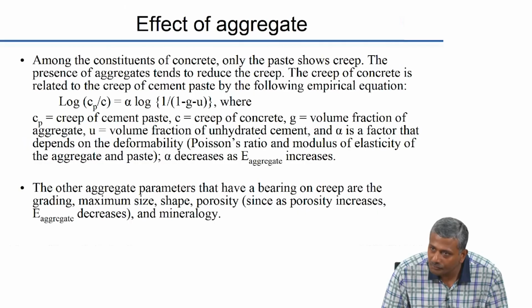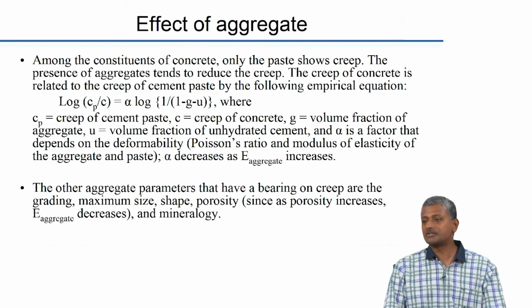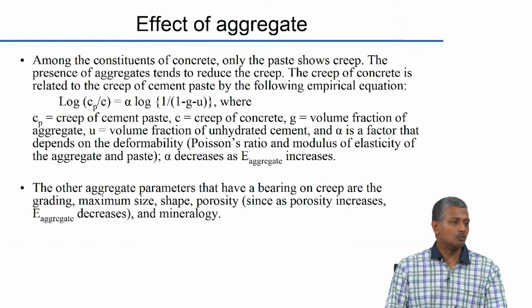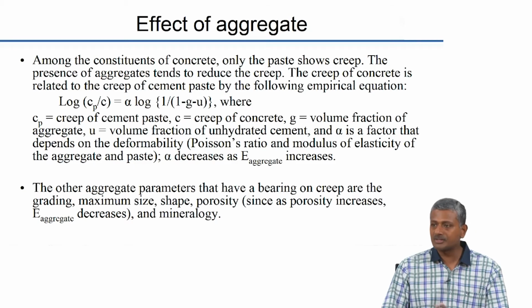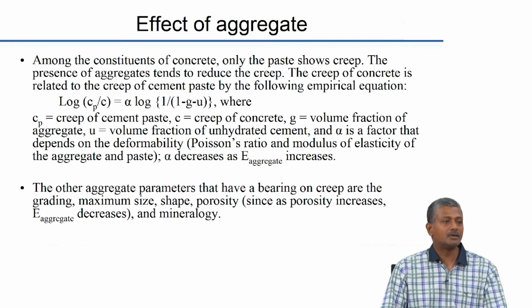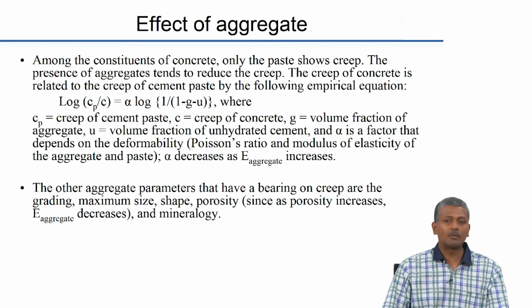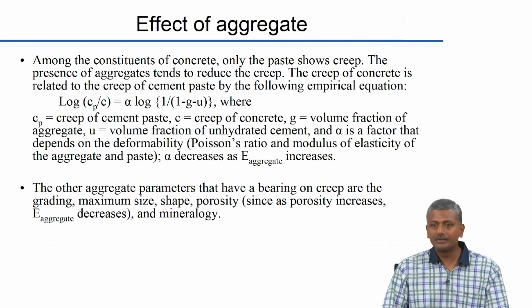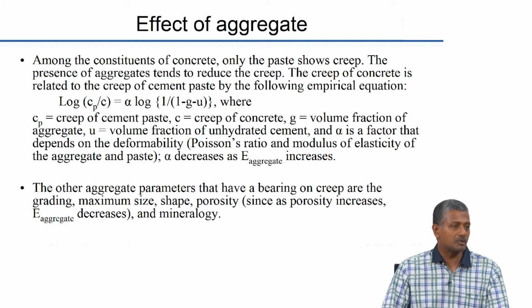faster. Now, we know that it is only the cement paste which is going to be subjected to volumetric deformation. The aggregate for the most part is going to be inert to the effects of conventional working temperatures and the extent of drying that happens in real conditions. So, what research has shown is that the creep of concrete is inversely proportional to the amount of aggregate that you have in your system. The greater the amount of aggregate, the lesser the creep in your system.